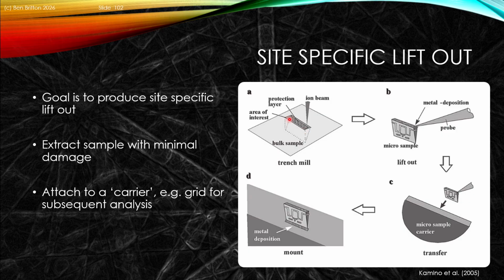Above this layer, we'll then cut out a sample. It can be wedge-like or parallel-faced. We'll attach it to our lift-out probe or needle, and that sample will then contain the features in this cross-section. We'll then effectively stick this very small sample, often say 5 micrometers by 5 micrometers in size, onto a mount or grid that can be manipulated by a pair of tweezers or similar, typically vacuum tweezers these days.